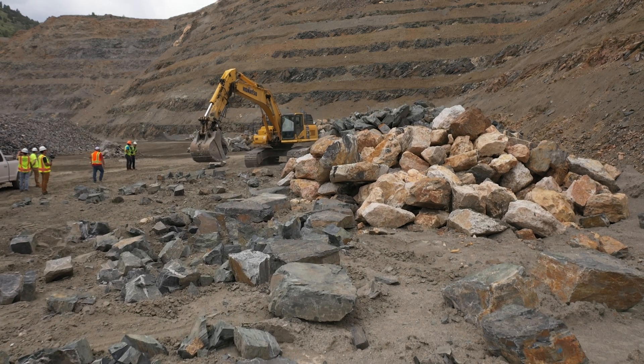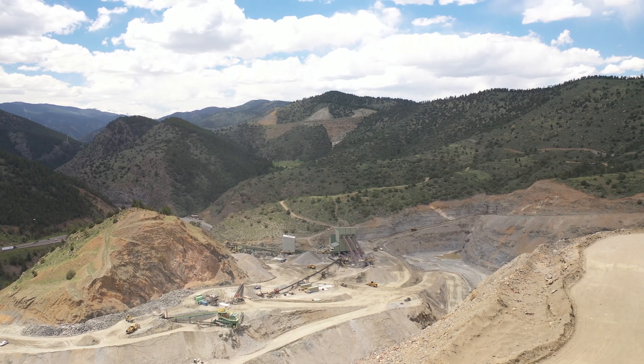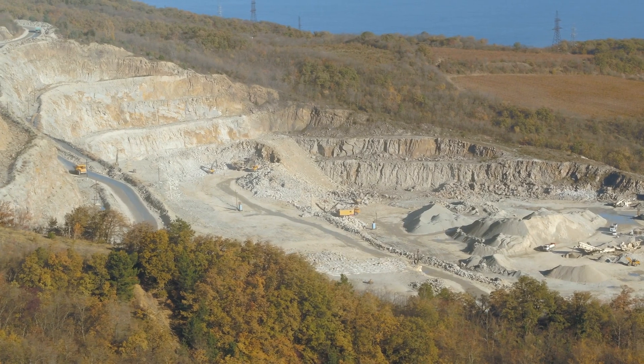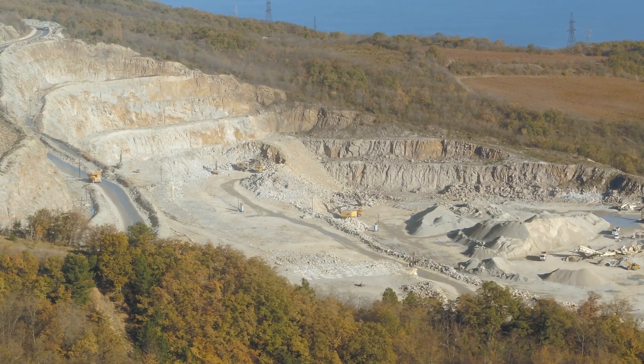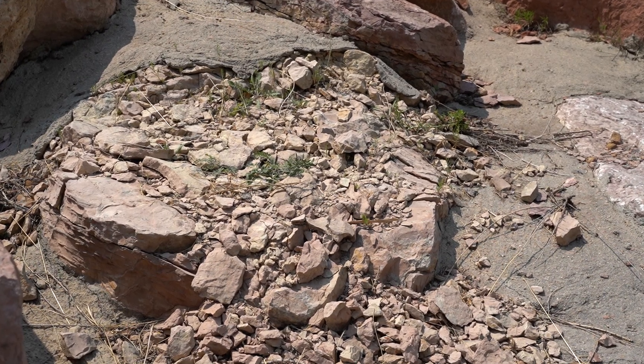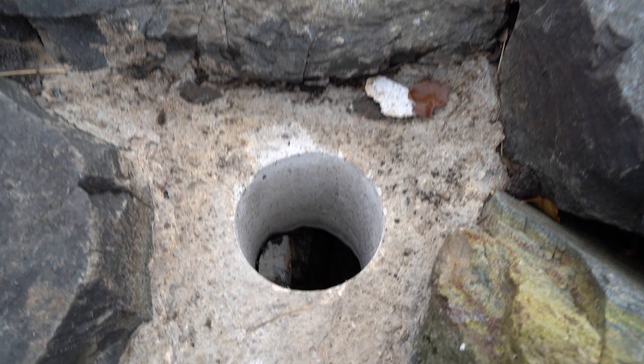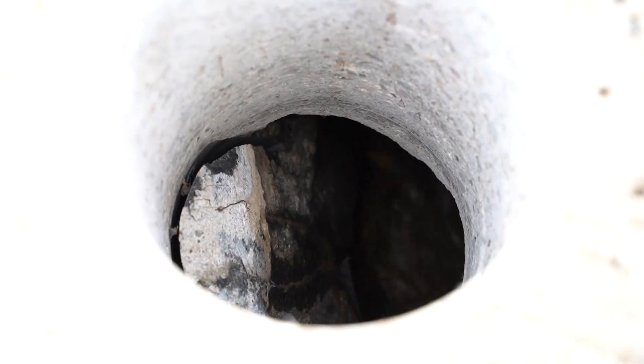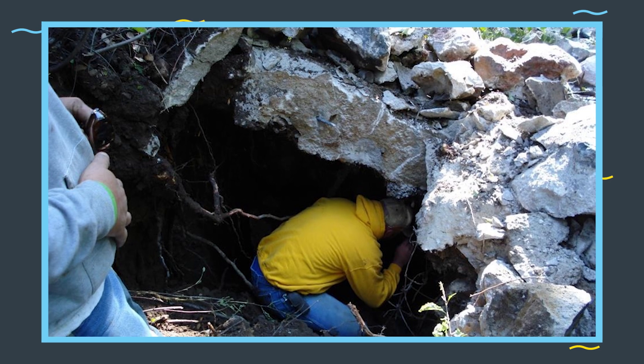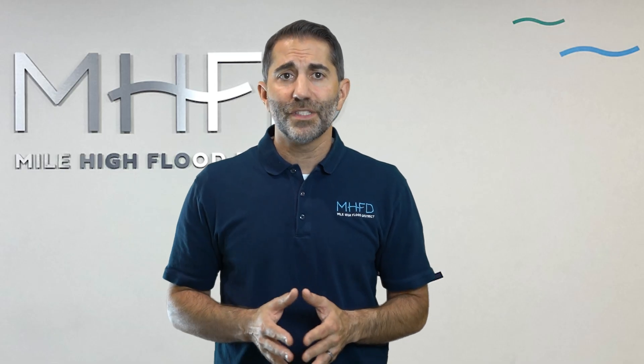It's critical to use high quality rock for grouted boulder structures. Most of the boulders produced in Colorado come from mountain quarries in granite formations that produce rock that is heavy and durable. However, there are some quarries that are not in granite formations and produce less durable rock that can disintegrate over time, as you can see in this drop structure. These started out as solid 36-inch boulders that disintegrated into potato chip-sized fragments. Grouted boulder drop structures need to have a watertight connection between the grouted boulders and the seepage cutoff wall. If the connection is poor, it can lead to a piping condition where subsurface flows erode the underlying subgrade soils and create large voids under the structure, resulting in significant damage and even total structural failure. For guidance on proper construction of seepage cutoff walls, please refer to the district's website and other instructional videos on our YouTube channel.